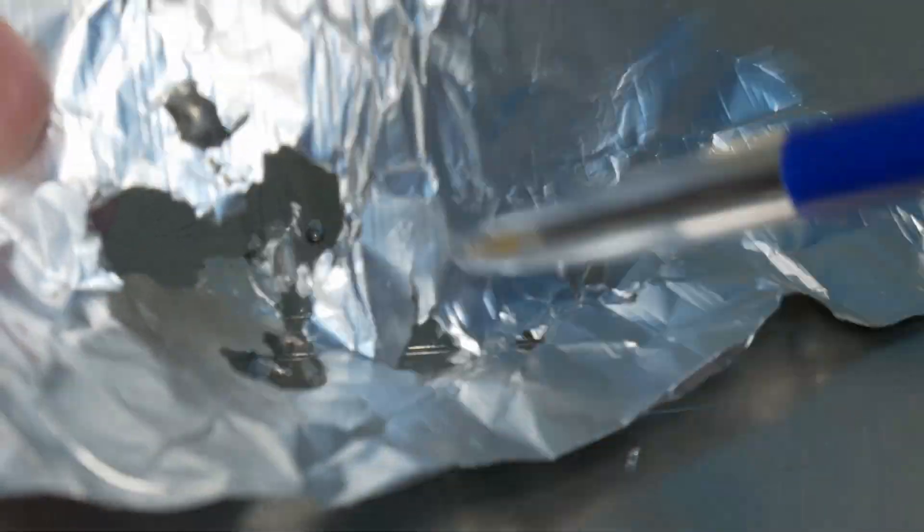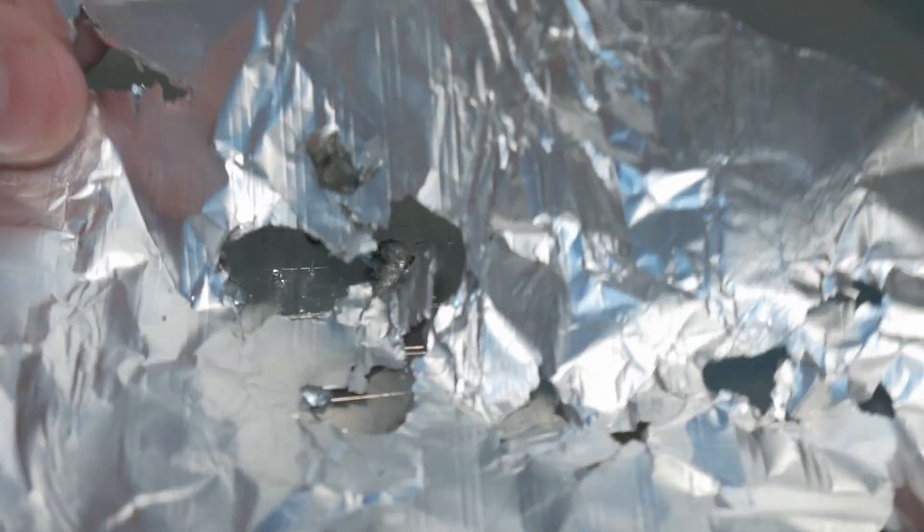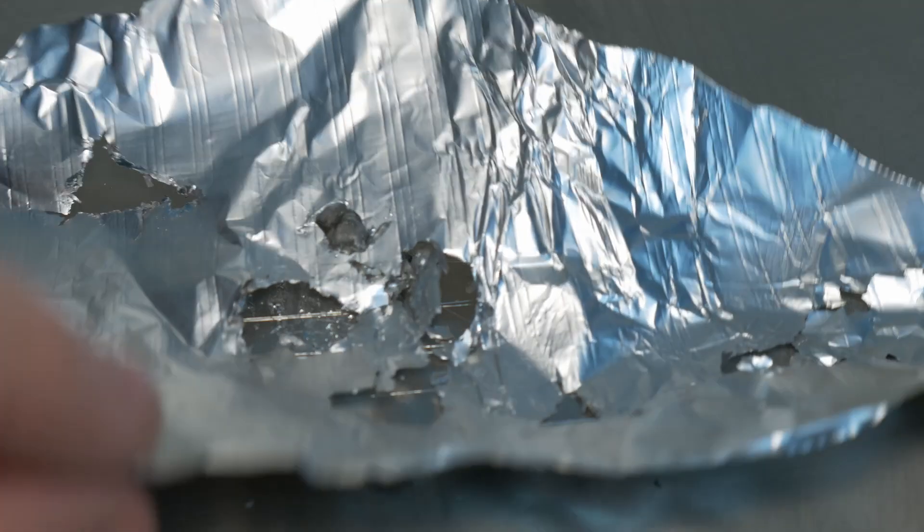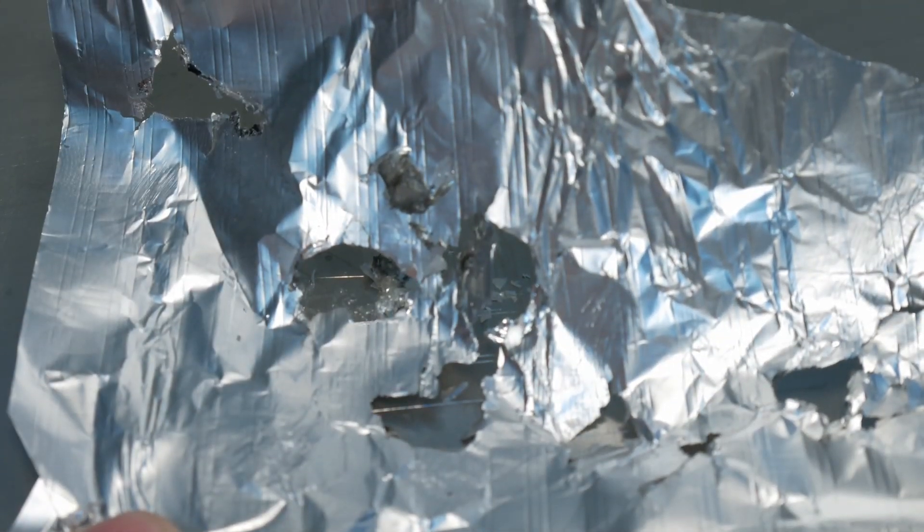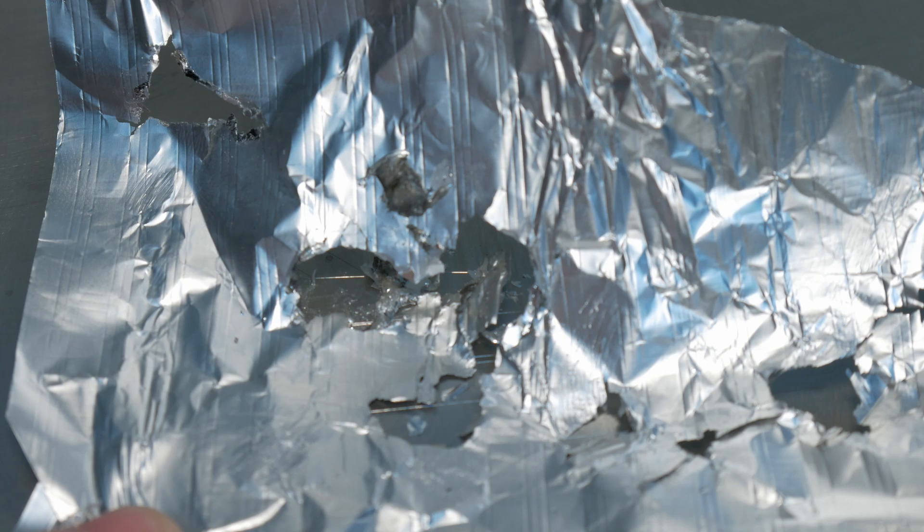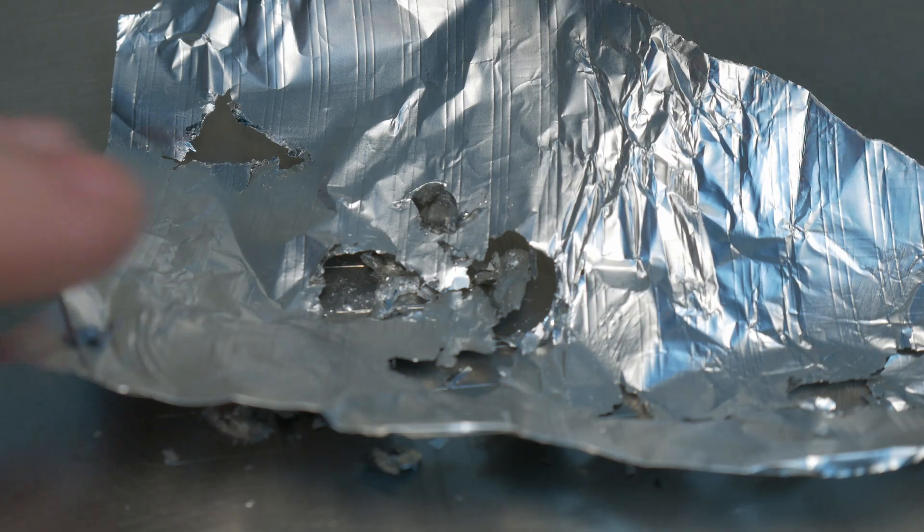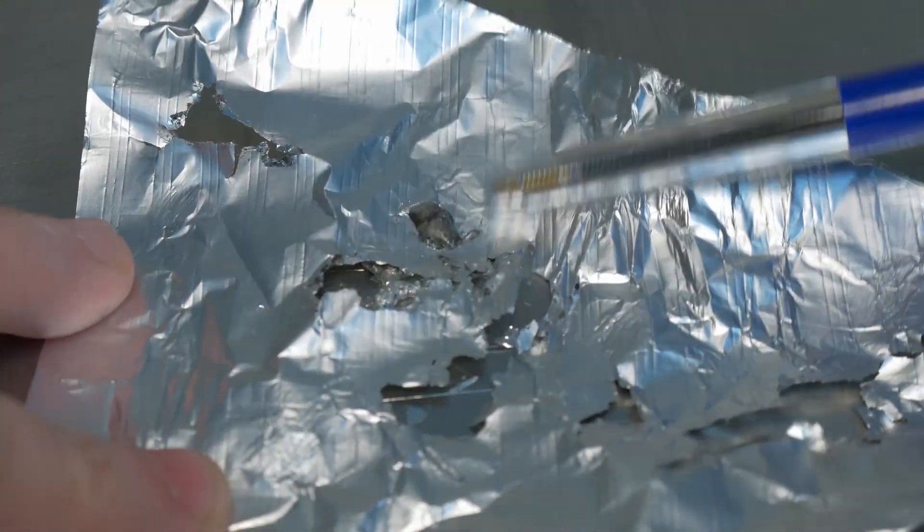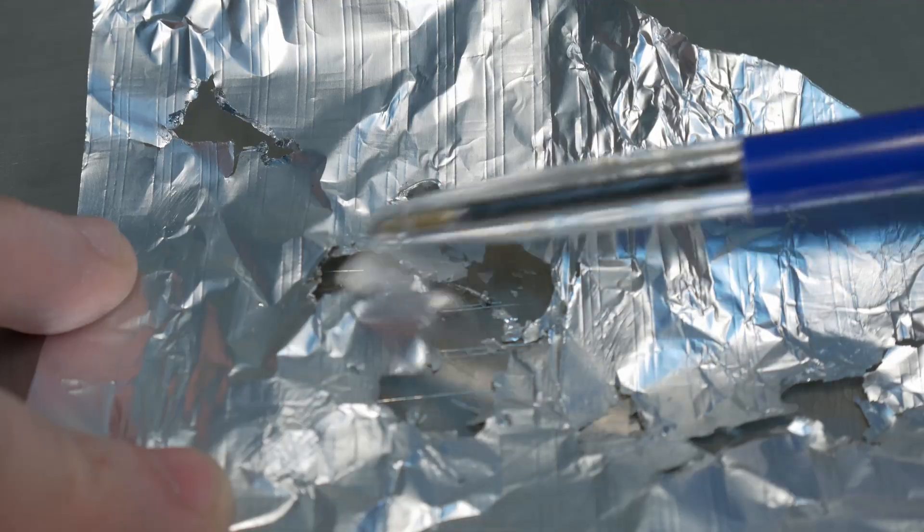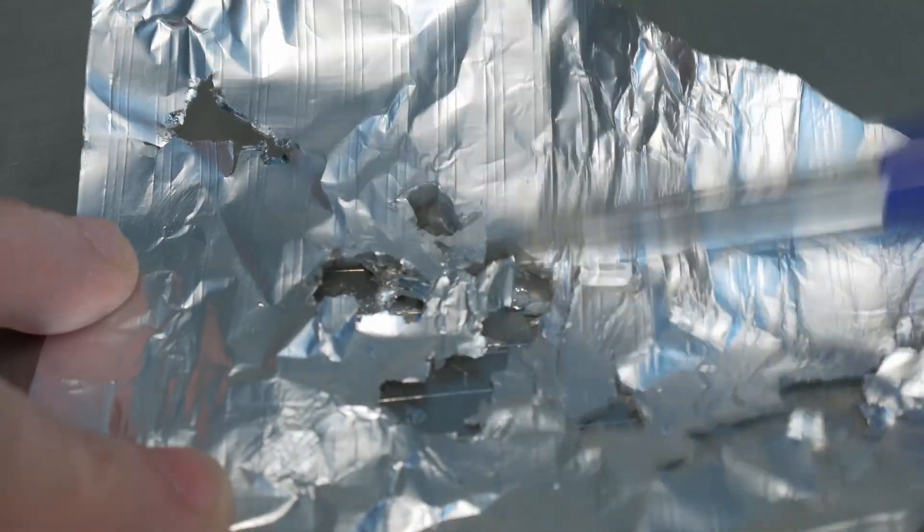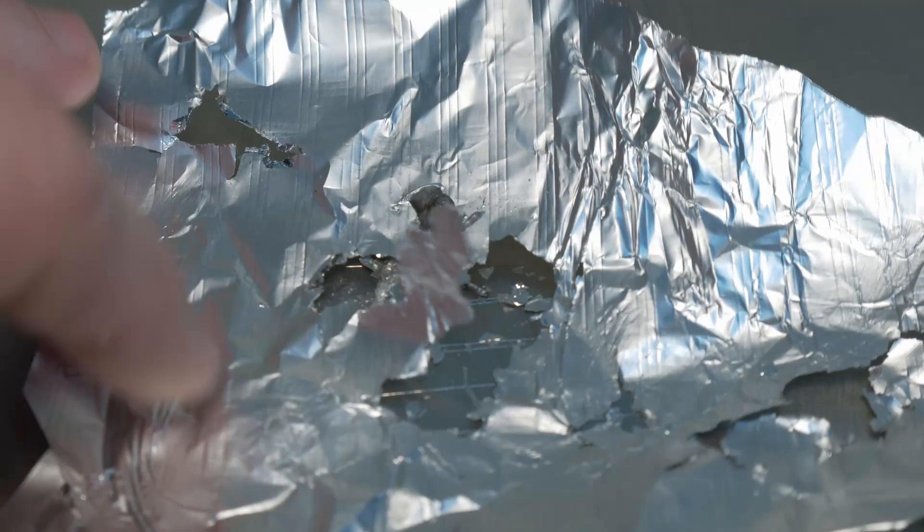Now we've now created a perfect, if ragged, hole in a piece of aluminum without using any mechanical drilling. Now we can expect a hole. The edges might be a little bit crumbly or crystallized and the gallium treated area is extremely weak, crumbling at the touch, whereas the surrounding metal is still hard. Now it is a dramatic before and after difference. You essentially gave aluminum a cavity using gallium and then poked it out. This is the same effect localized. Gallium can eat a hole through aluminum by making that region feeble. If this were a boat, it would definitely be leaking by now.